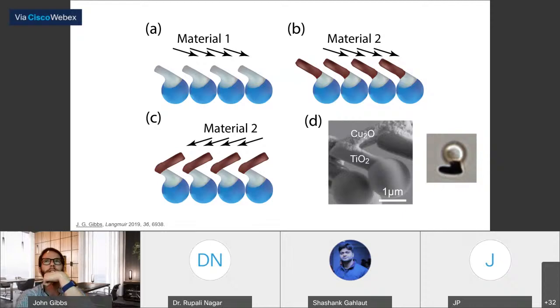Okay, so it didn't really turn out exactly the way that we wanted it to, because one of the problems is that, as you know, if your photon has a high enough energy to make the transition from the valence band to the conduction band, that's going to occur for a higher energy photon. So what I mean by that is that if you can excite this band gap transition in copper oxide, when you use ultraviolet light, you can make that transition in TiO2, but it's also going to be able to make a transition for the copper oxide. So that was a bit of a bottleneck that we never really quite got around.